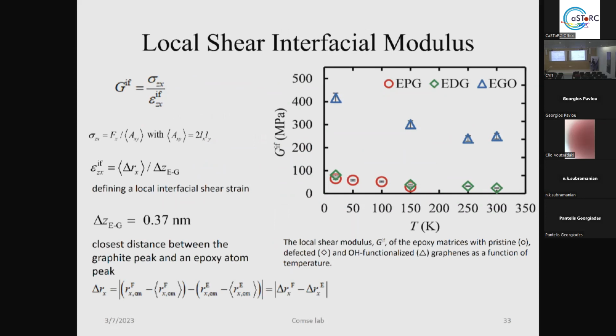If you have a specific value of F, and then from this F you compute the delta R, right? And then from the ratio you get G. So my question: if you change F, you will get the same value of G? If I understood the question right, this is what we're doing. We change the shear stress, and thus we change the F, right? Yes, exactly. So you apply force on the graphene, and from the force you compute sigma. Exactly. And then delta R and then epsilon, and then you will obtain G.